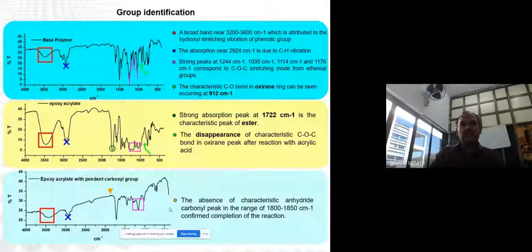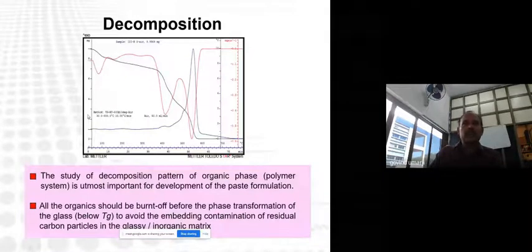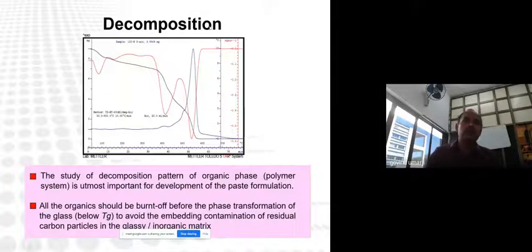Once we understand the reaction got complete, we also study the decomposition of this Novolac epoxy. Since the Novolac epoxy is known for its good thermal properties, we studied that for considering our paste formulation. We can see that all the organic burns. There is a requirement that it should burn before the phase transformation of the glass, in order to avoid the embedding of the contamination or the